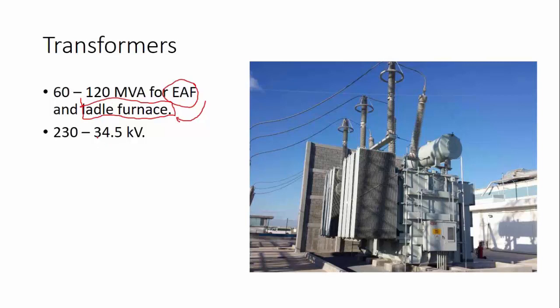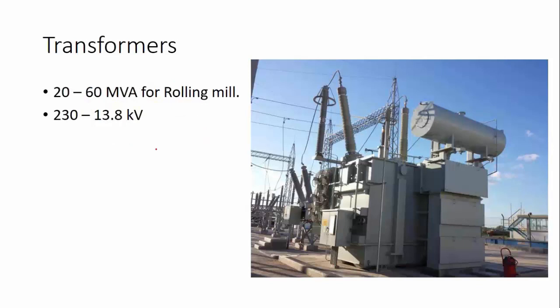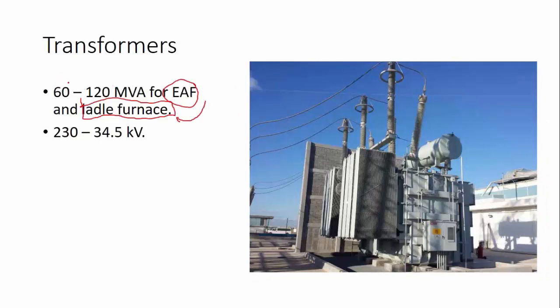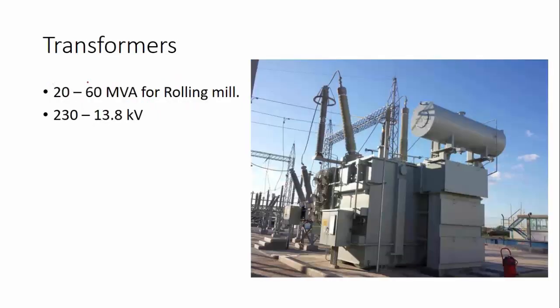These transformers are typically 230, 34.5 kilovolts. This is a very typical arrangement in an electric arc furnace facility. Now, next to it, we'll have a much smaller transformer, which is 20 to 60 MVA. The electric arc furnace transformer typically goes from 60 to 120 MVA. It's very big. This one is much smaller, and it's for the rolling mill. It's just for the machines that will treat the already molten steel, the rolls of steel, the rolling to the desired width of the steel. Normally, this part of the plant is handled at 13.8 kilovolts, at least here in Mexico.